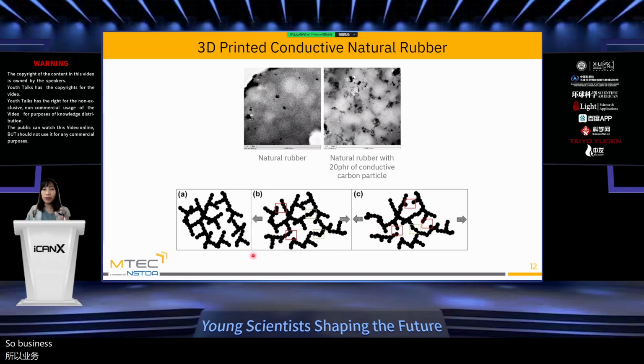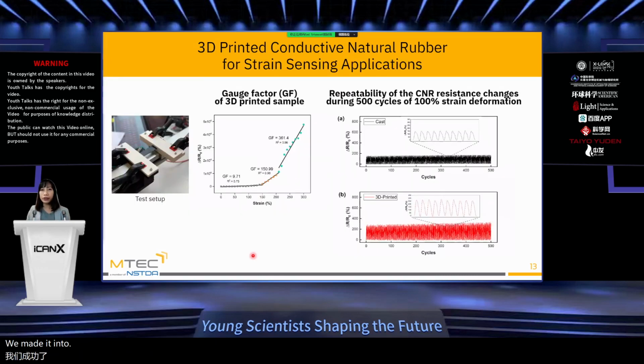So with the fundamental of how you make the network less dense so that you can detect the signal of your material, we made it into a strain sensor or a strain gauge. In the picture on the left, that's our sample. This black one is our sample. We clamp it between two grippers and slowly pull it apart. When you stretch your sample longer and longer, you will see a change in the resistance, as plotted in the graph in the middle here.